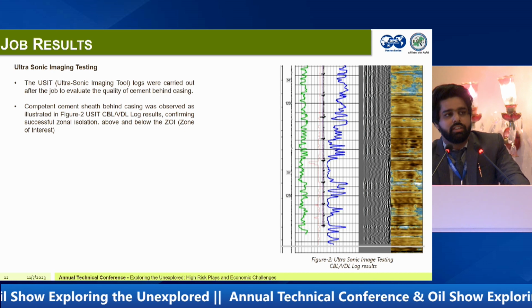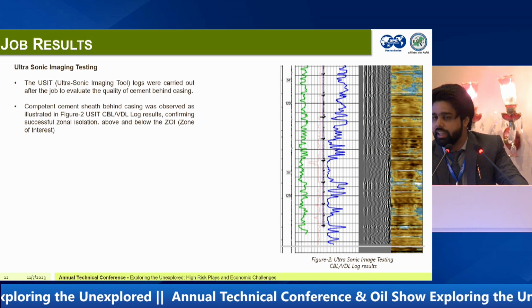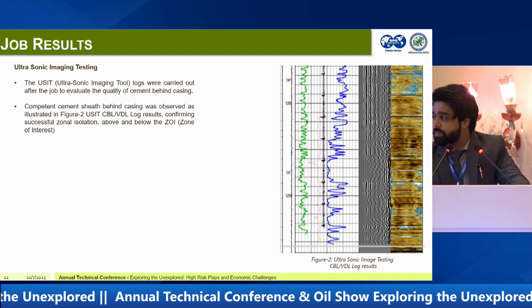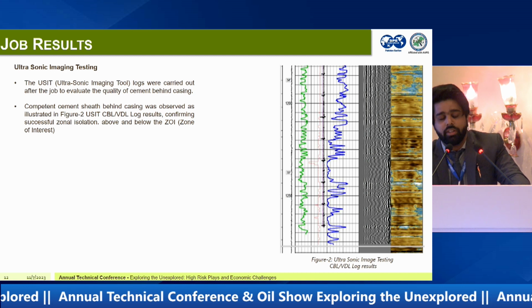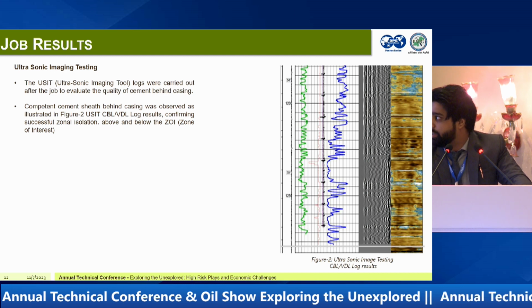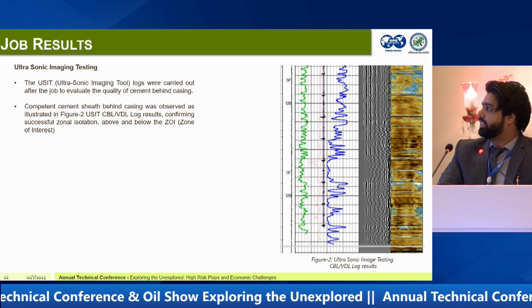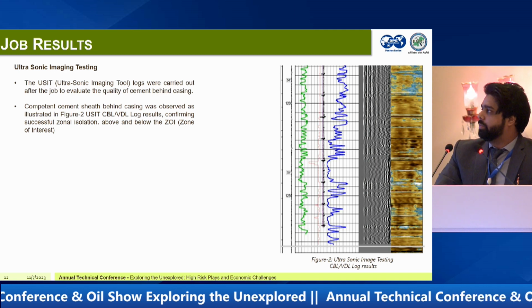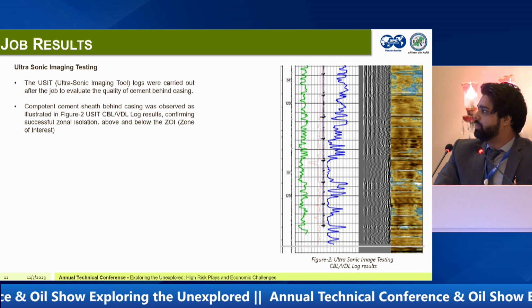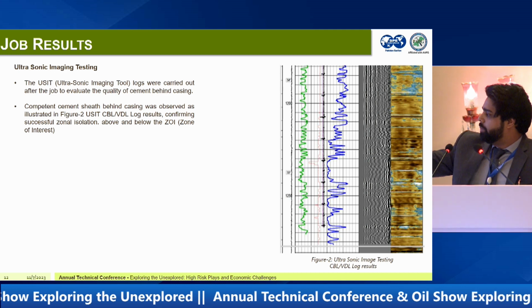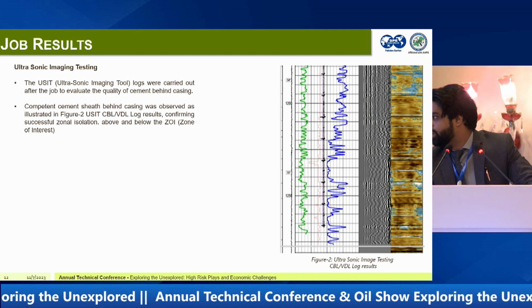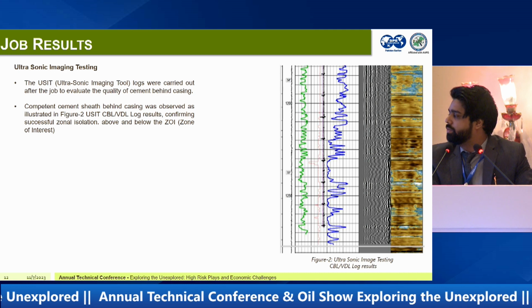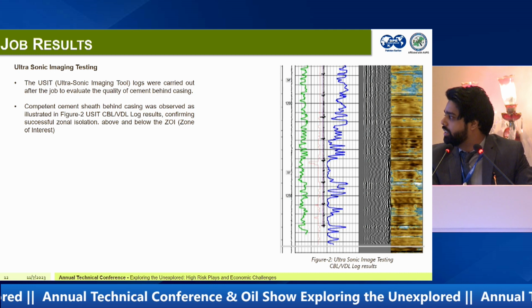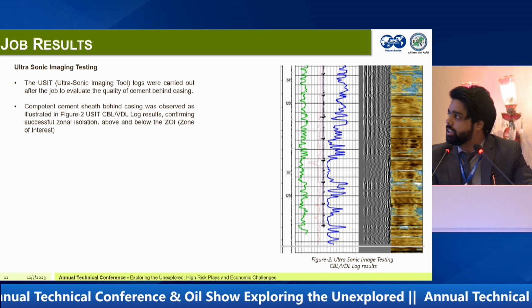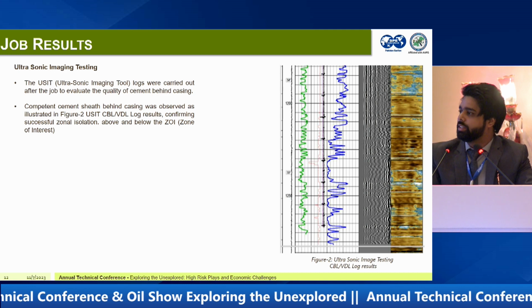These are the basic job results that we gathered, and we performed a successful cement job considering flexible cements. We performed an ultrasonic imaging tool log, and we also have an image that you can see with low amplitude, strong formation signals, and also radial coverage around our zone of interest.